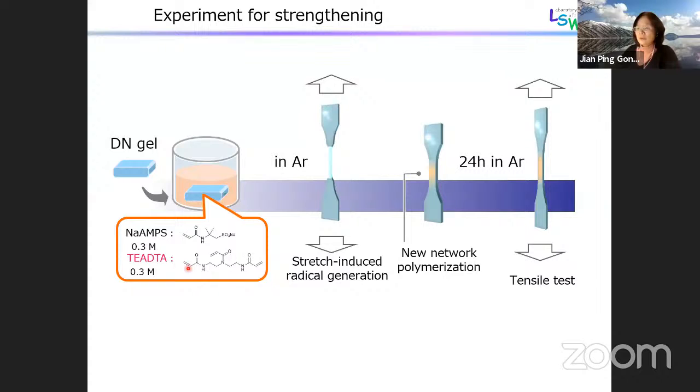Here, in order to increase reaction efficiency, we use a 3-functional crosslinker. You can see there are 3 vinyl bonds, double bonds here, and if all participate in the reactions, it can form networks with 3 chains connected on the network. So we soaked the gel in this kind of solution, and also did the stretching and the polymerization and the mechanical test in this case.